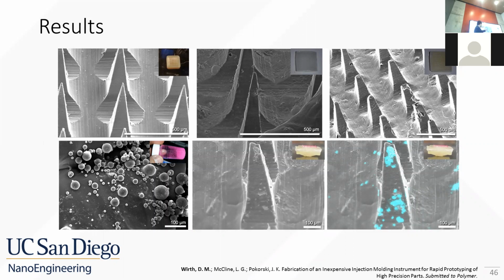Here's what that looks like - you can see still relatively sharp tips, very good fidelity. We can then transition to a dissolvable polymer such as polyethylene glycol, and you can see these are still fairly close to the original tips. There is a bit of dulling, but otherwise fairly good geometric reproduction.